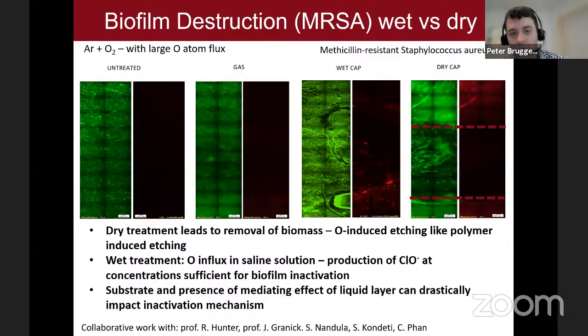And so here we just look to conditions where biofilm is kind of a very thin layer, hundreds of micron maybe, at the surface. And so when you have a liquid layer, what basically the plasma is doing is it's bringing species in the liquid, and you see kind of inactivation, which is the red curve. So the green means biomass, and if you see red, it means there is inactivation. So you see in the controls, the two left cases, nothing. You see that the plasma is inactivated. You see a lot of red. But remarkably, when you do it in dry cases, you see that there is kind of a depleted zone in the green, and there is no red. Well, there is a lot of red on the edges, where you're actually suggesting you are removing the biofilms.